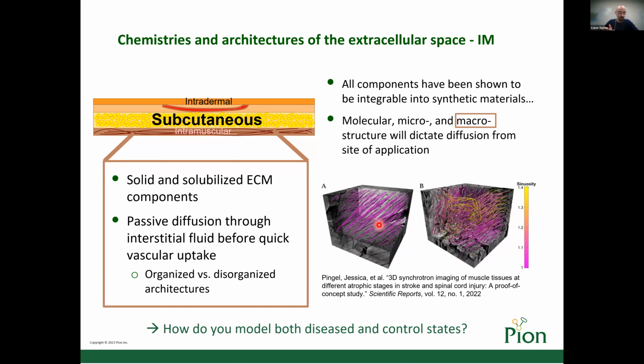Everything is aligned in parallel so that when we look to mimicking this kind of environment, we understand, okay, when we finally get to the point in which we are introducing solid fibers of collagenous material, we need to align them at this angle, at this spacing, in order to achieve the same diffusion kinetics that happen inside this environment. After a stroke or after a disease state, you can see that the linearity of these fibers changes. And that means that you will simply have a different diffusion coefficient simply by the solid architecture difference within the same injection site.